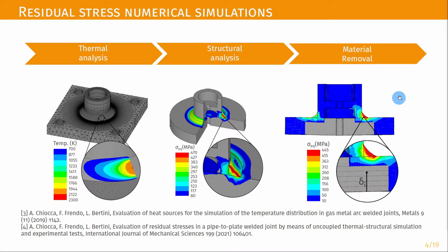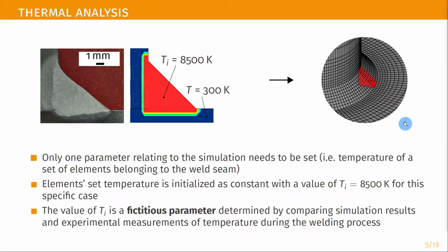These strains were experimentally measured using strain gauges and by incrementally drilling the specimen from the bottom of the plate after the welding process. To simulate the thermal load deriving from the welding process, a constant initial temperature method was implemented. The thermal process was initialized by activating a volume of elements at a starting temperature Ti, where Ti is the only parameter this method needs to work properly.